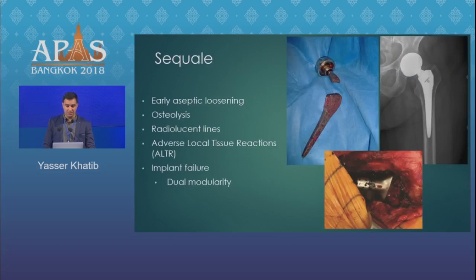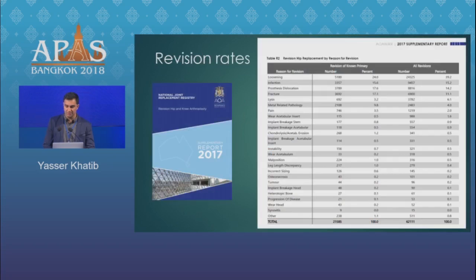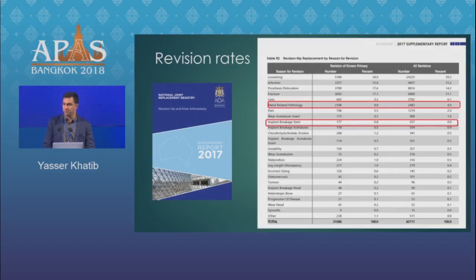We see the sequelae, which are early aseptic loosening, osteolysis, the presence of radiolucent lines. We also see tissue reactions develop. And of course, what we worry about is the implant failure, especially common with the dual modularity type implants, which have largely been abandoned. If we look at the Australian registry experience, some sort of metal problem appears to be the cause behind revision in hips between 5 to 10% of the cases.